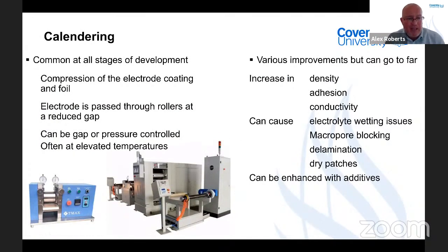Calendaring is the next stage that we'll look at. And this is very simply the compression of the electrode and the current collector together. And you can do this in a number of ways. We often do it at higher temperatures. And you can put something through a fixed pressure or through a fixed size gap to reduce the area it goes through. And this can increase the density and the adhesion. And by bringing everything together, it can increase the conductivity of the electrode as well.